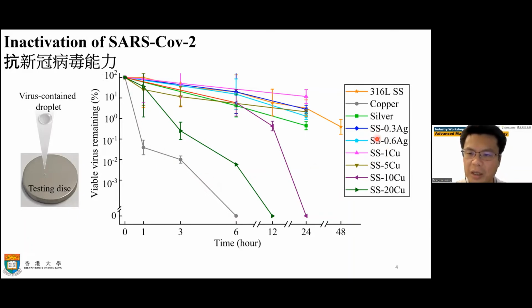Then we used powder metallurgy technology to make stainless steel. SS stands for stainless steel, containing different silver contents and different copper contents. For stainless steel containing silver, the blue line and this light blue here, you see it does not have antivirus properties. Then we checked 1 weight percent copper, 5 weight percent, 10%, and 20% copper. You can see the properties are different with different copper content.